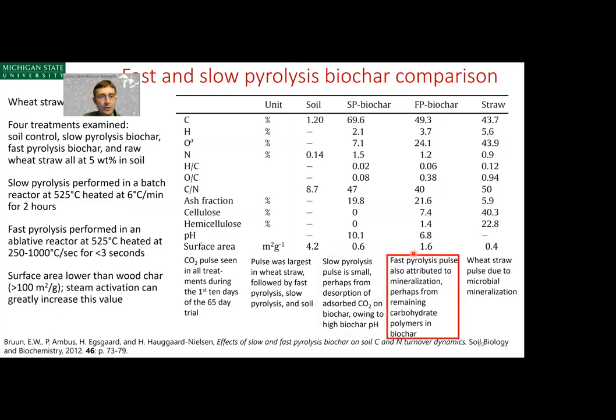Fast pyrolysis pulse was greater than the slow pyrolysis pulse, and they attributed this to the fact that fast pyrolysis had a larger content of carbohydrate polymers, which microorganisms perhaps were able to access quite easily. And the microbial mineralization rate from wheat straw was quite large.